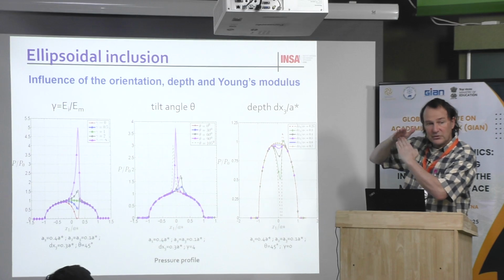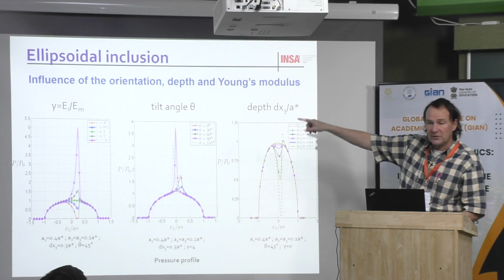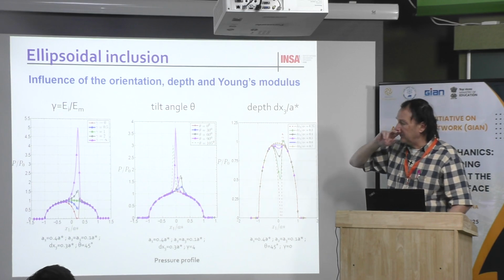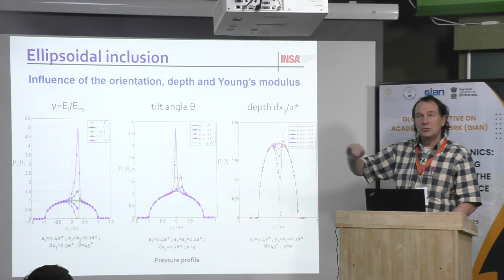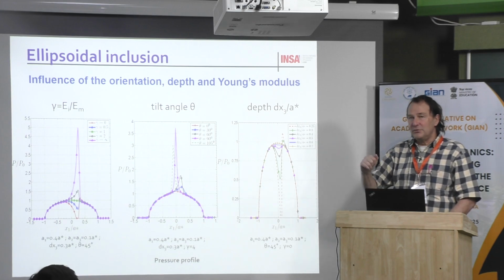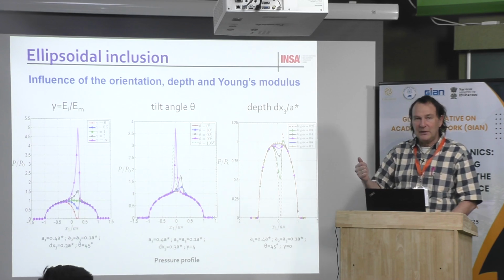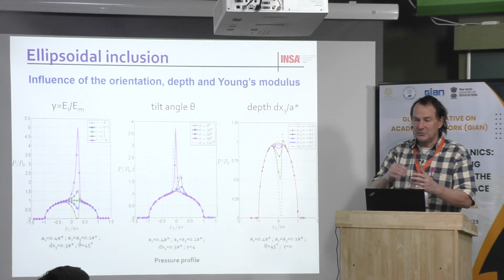Then it's tangent to the surface. And because it is rigid, you can have a very strong peak of pressure. Now, if you assume that your composite material is a polymeric matrix with some carbon fiber inside and so on, you may calculate the equivalent Young modulus, calculate the contact pressure and so on.